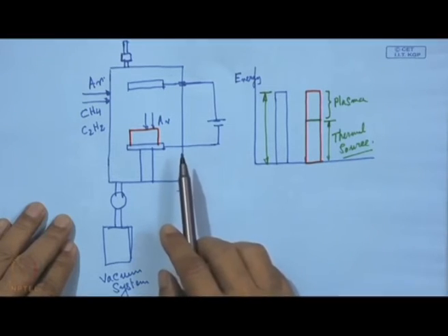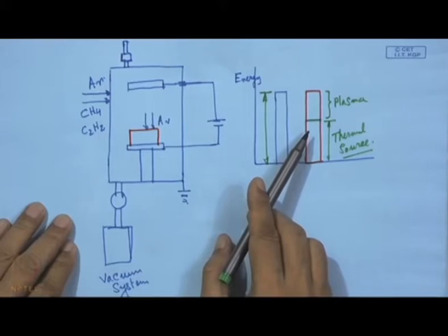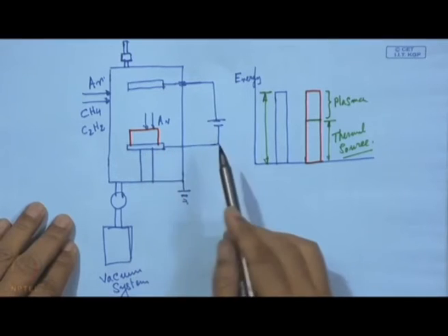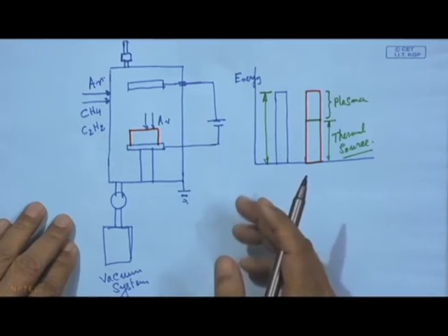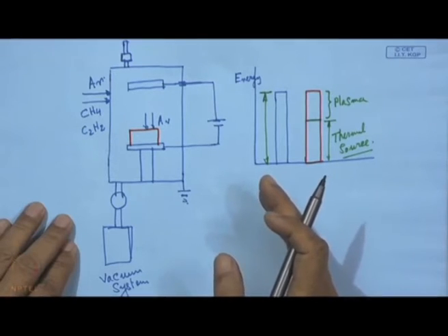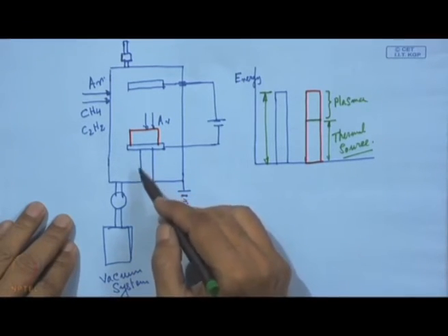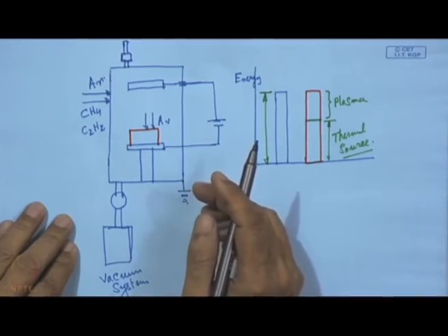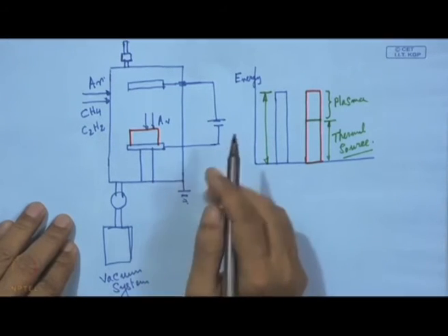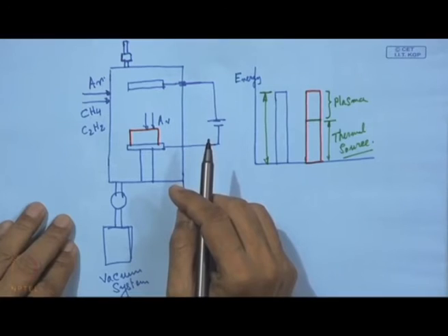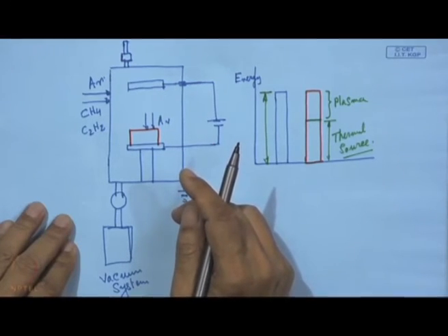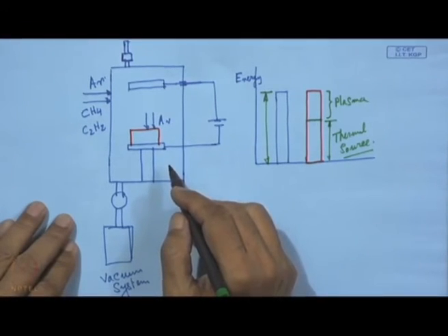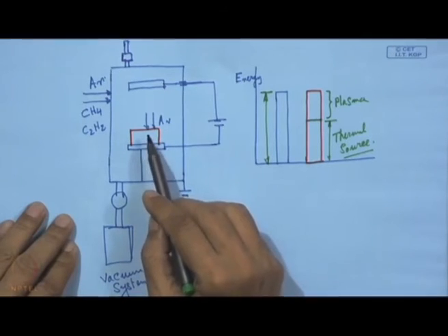Just by reducing the temperature requirement, the whole process can be conducted in the range of 200 to 300 degrees centigrade, and with all new power supply devices it is possible to hold the temperature in a range where steel components won't undergo any sort of distortion, and can be taken as a finished product, and can straightforward undergo this